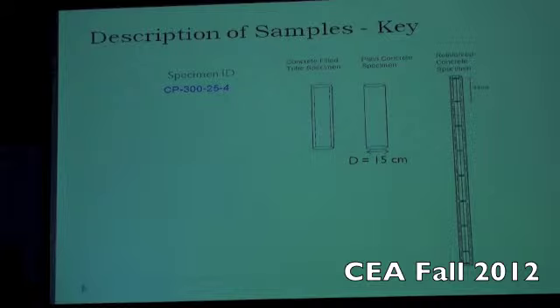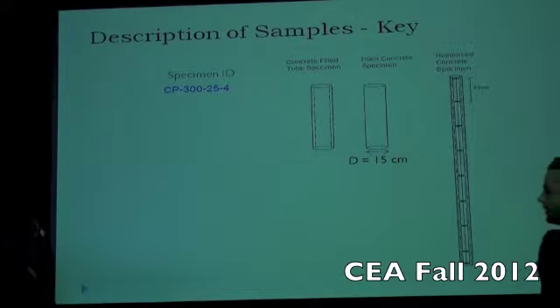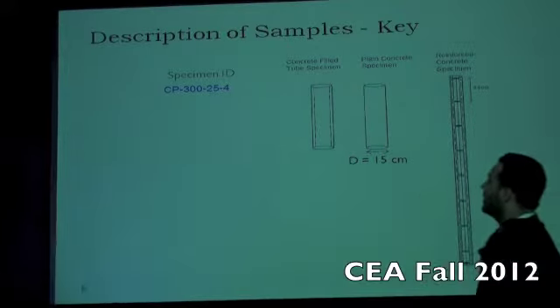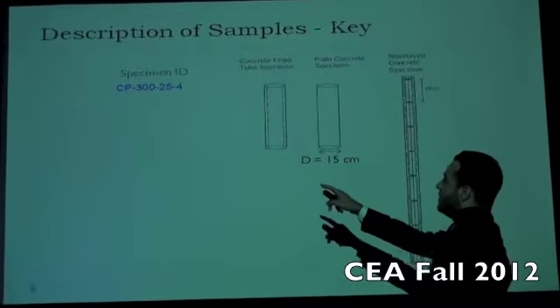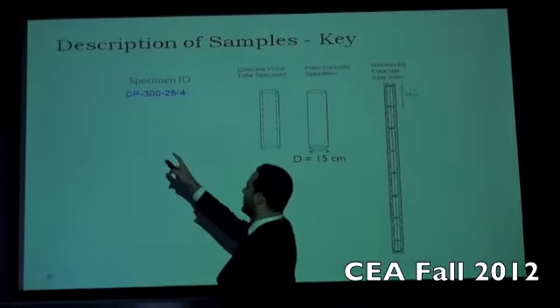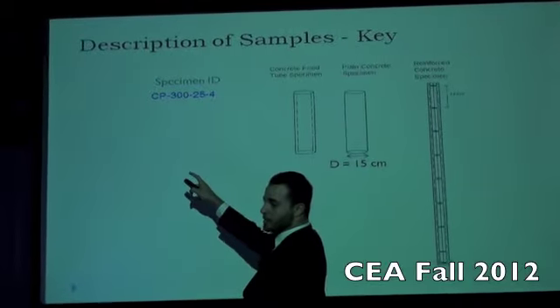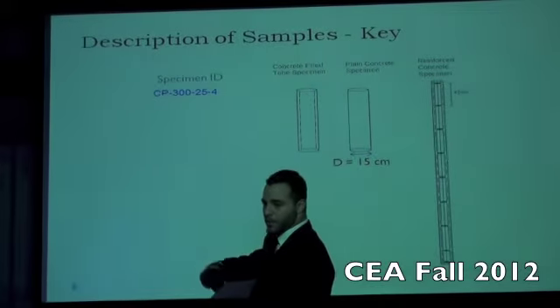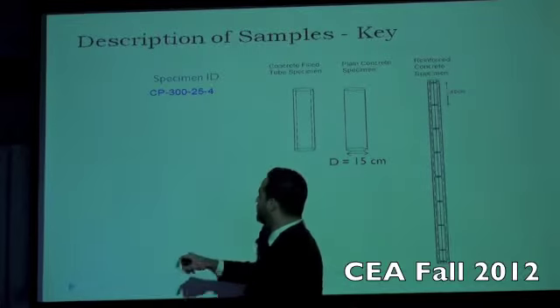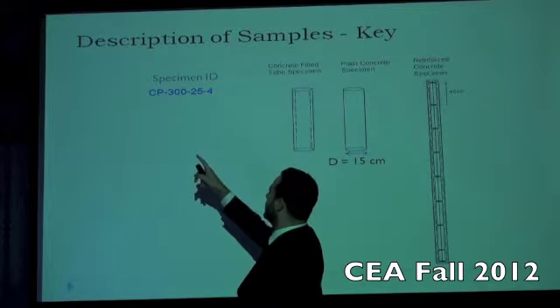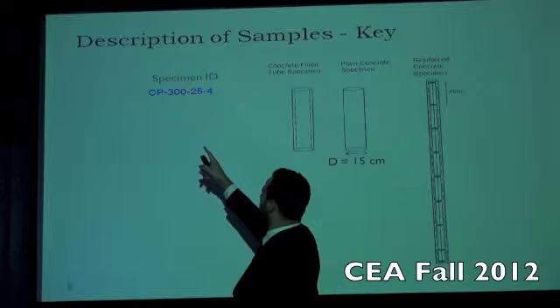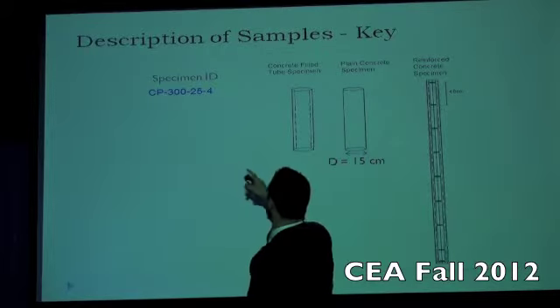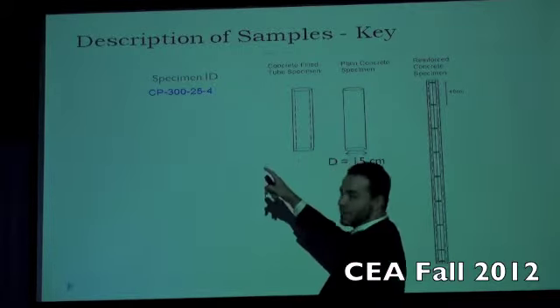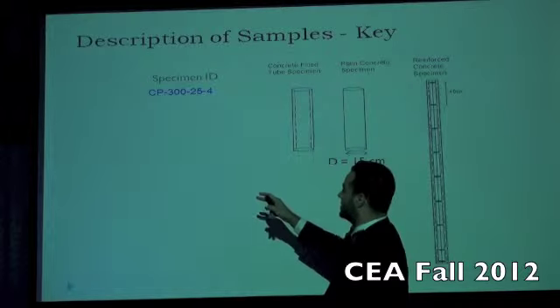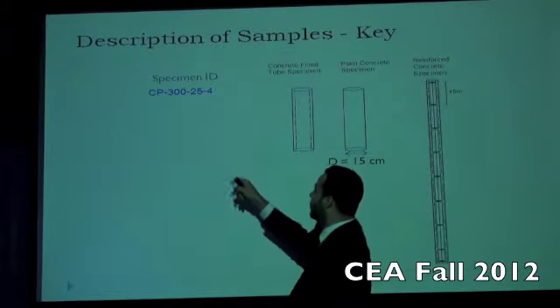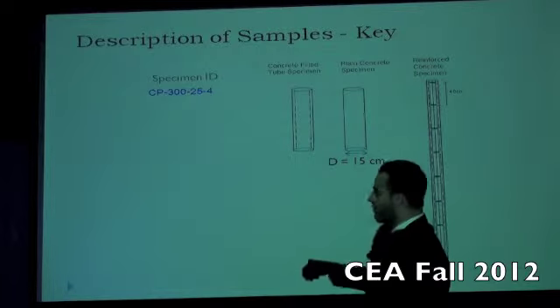Okay. And here is the description of our samples and preparing it. I put a code for every sample. CP means completely filled pipes, because we have both pipes with concrete and plain concrete without pipes. So CP means with pipes. This 300 is the height of the sample, and 25 is the strength of concrete, because we have two different strengths, and 4 is the bar of the pipe, because we have 4 different bars.